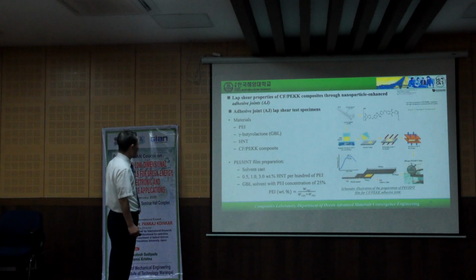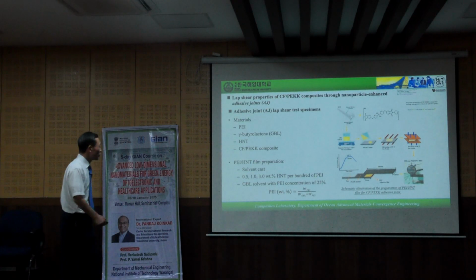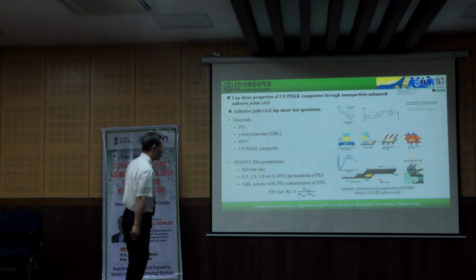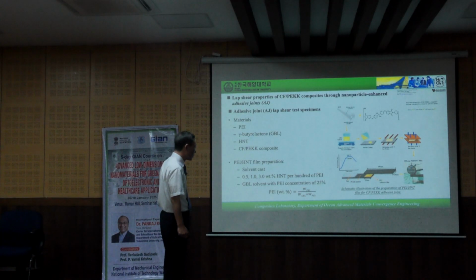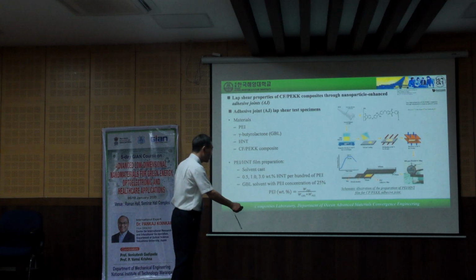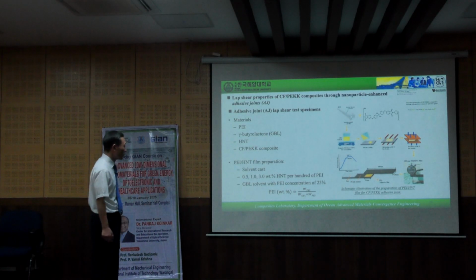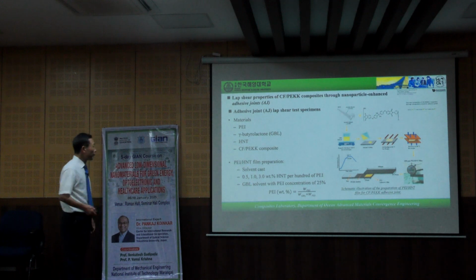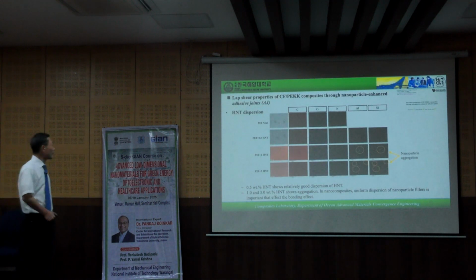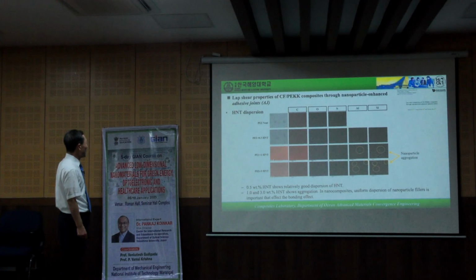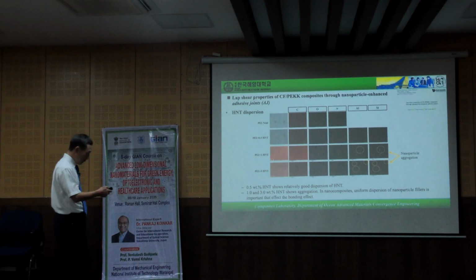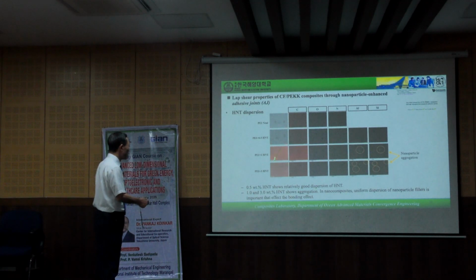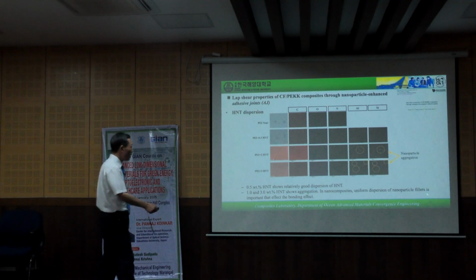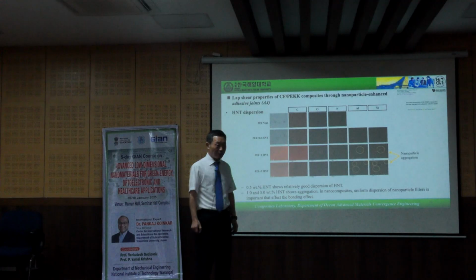This slide shows the lap shear properties of CF/PEKK composite through nanoparticle enhanced adhesive joint. We prepared the specimen like this. Schematic illustration of the preparation of PEI, HNT means halloysite nanotube, film for CF/PEKK adhesive joint. We observe HNT dispersion situation. In case of 1% HNT and 3% HNT, we can observe the nanoparticle aggregation.